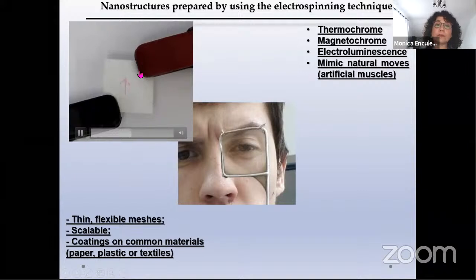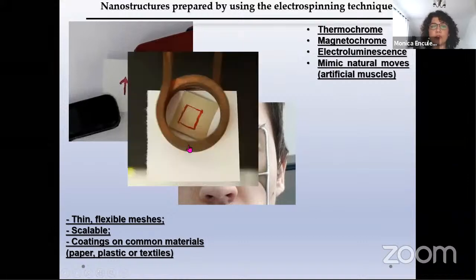You see, by applying a voltage, we can make the ink, the sign, disappear. Because on the paper, there is a very thin layer of nanofibers that are coated with gold. And because of that, we can make the paper conduct and change the color of the sign by applying a voltage.